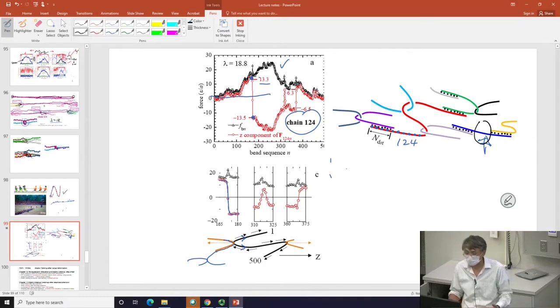And it just acts like one of the effective strands in the network. The rest of this history, meaning we are still in the middle of writing this up to publish it. But it tells you a very clear picture of how this entanglement network could manage to build enough chain tension in this network so that eventually the tension here is large enough for chains to break.